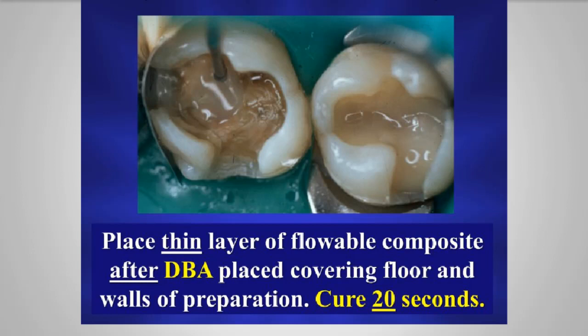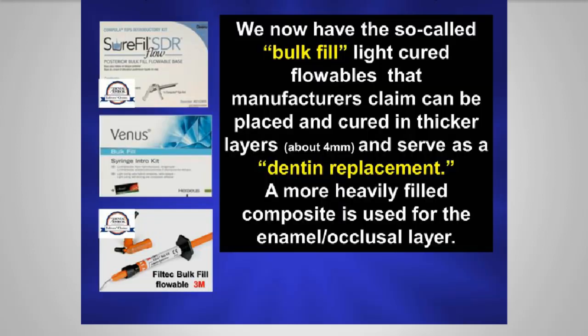And now we have something else. We have these so-called bulk fill light cured flowables. There's like 3 or 4 of them out right now. You can see some depicted here on the left. The manufacturers claim that these can be placed and cured in thicker layers, about 4 millimeters. Essentially they're serving as a dentin replacement. So you place them maybe 3/4 up in your preparation, then you place a more heavily filled composite material over that to use as your final occlusal or enamel layer. And this is not, by the way, a new concept. This is actually a very, very old concept.